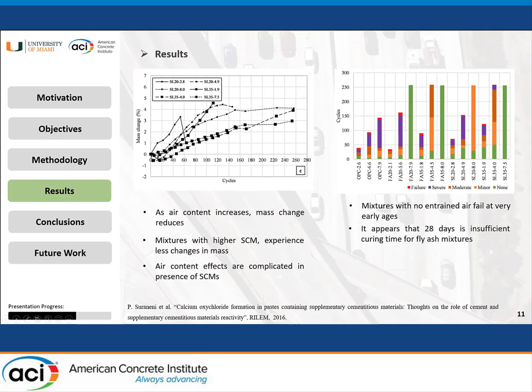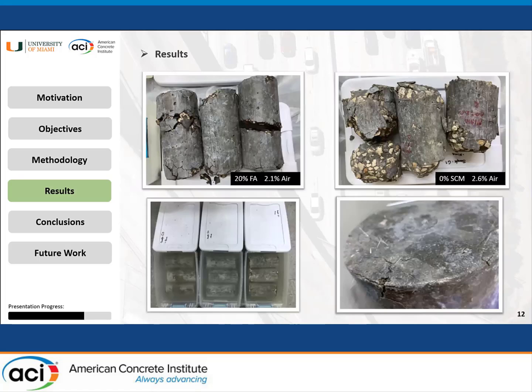And it appears that 28 days of curing is insufficient for the ones having fly ash in them. And both air and SCMs are significantly increasing the time to failure, as we can see here from left to right. And SCM type and replacement levels are affecting the time to failure significantly. Here I put some pictures that we had as we were measuring our cycles. You see how the samples are failing for samples containing fly ash versus samples having no SCM. And at the bottom right, you see the calcium oxychloride crystals that have formed on the surface of our concrete cylinders.